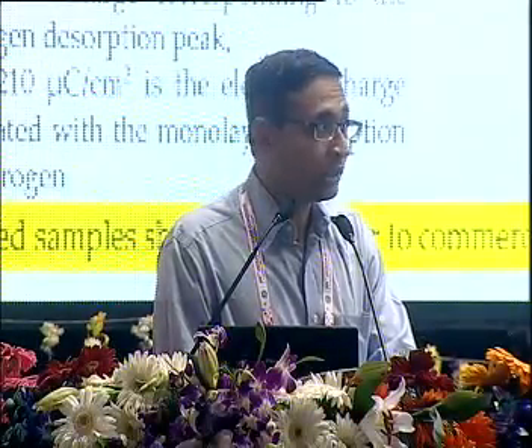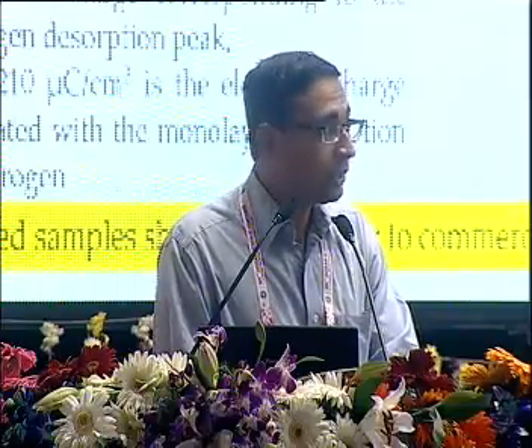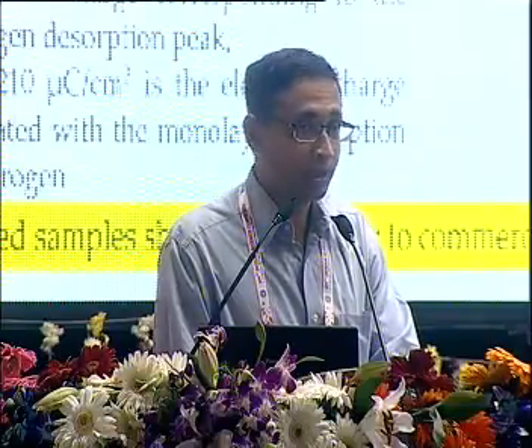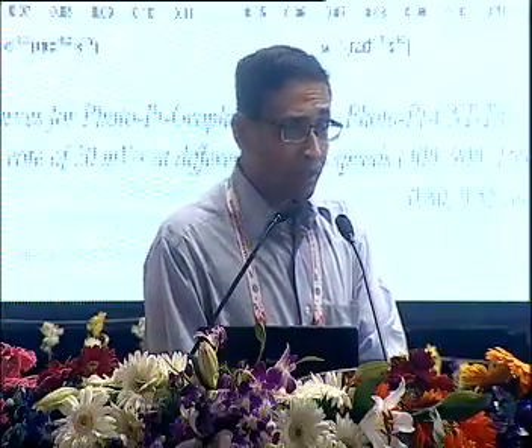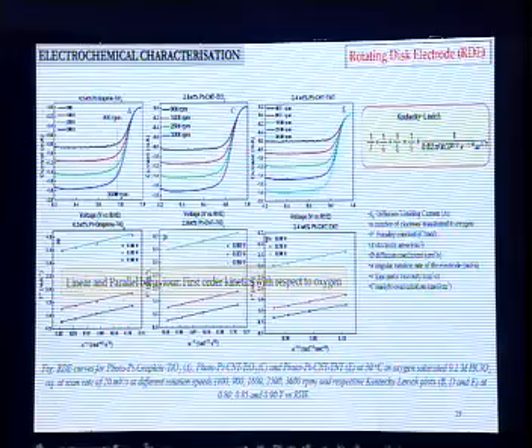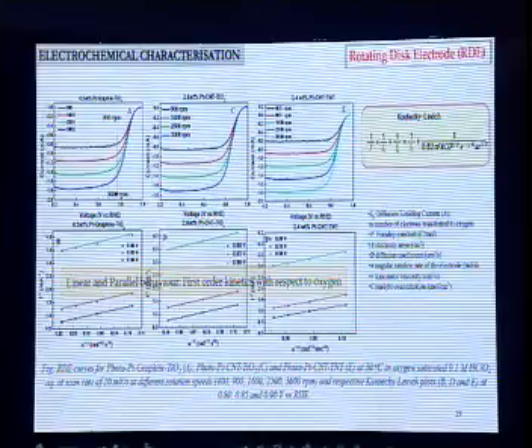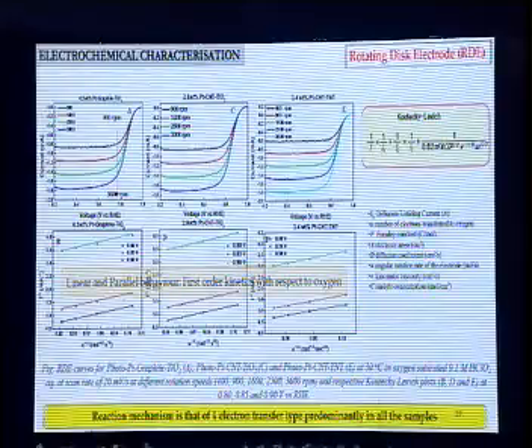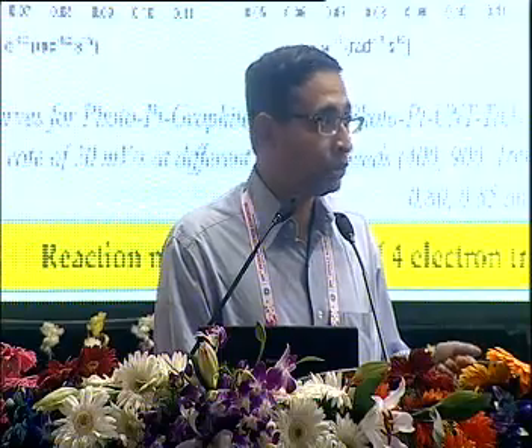which is 10 times lower than the commercial catalyst, and still it behaves as close to the commercial catalyst. Now there are other techniques which further substantiate that our electrocatalyst is usable, such as electrochemical characterization, which also depicts the mechanism in which the electrocatalyst can function. And we found that all these materials which we prepared undergo a 4-electron transfer mechanism, which is the most effective way in which the reaction can take place in a fuel cell.